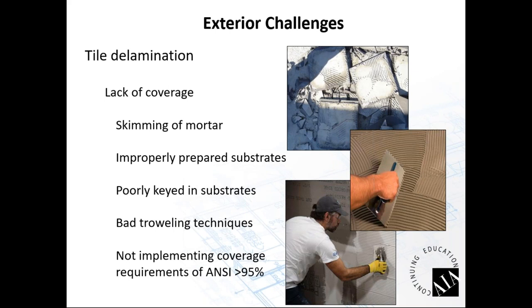He made sure that substrates are properly cured, that you're spreading the mortar in one direction, troweling it in, keying it in with the backside of the trowel, and then spreading your proper amount of mortar with the notch trowel. Troweling in one direction, maybe going in a couple of directions, but then your final pass is all in one direction so that the mortar is directional, so that you're locking together your tile and your mortar on the substrate. Then always remember implementing that greater than 95% coverage, critical parts.